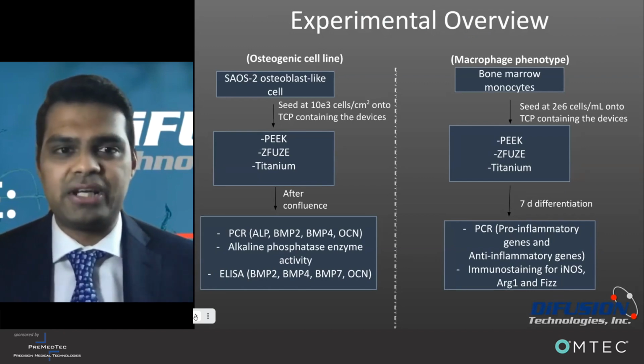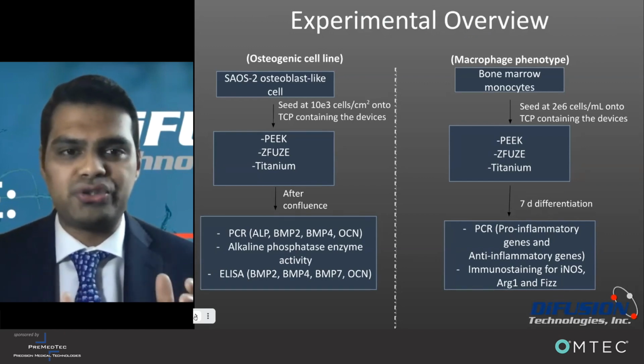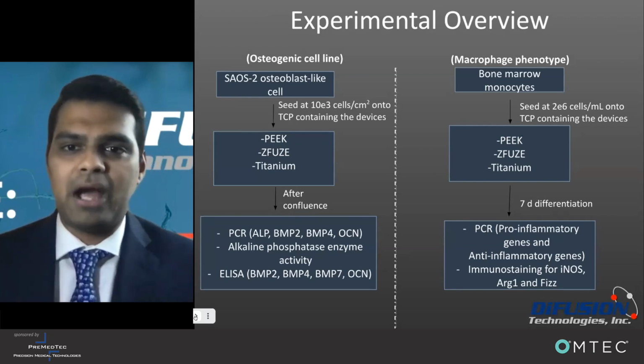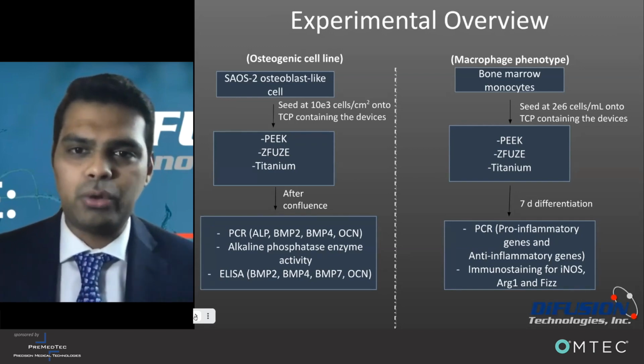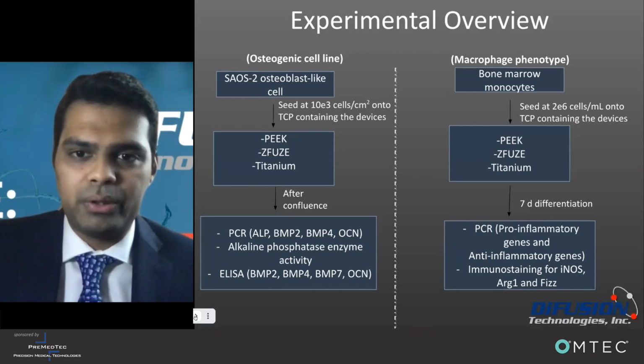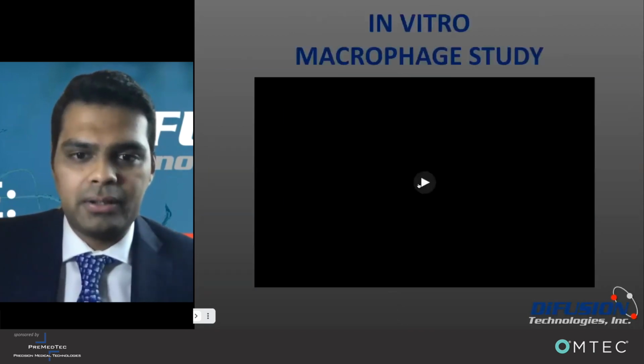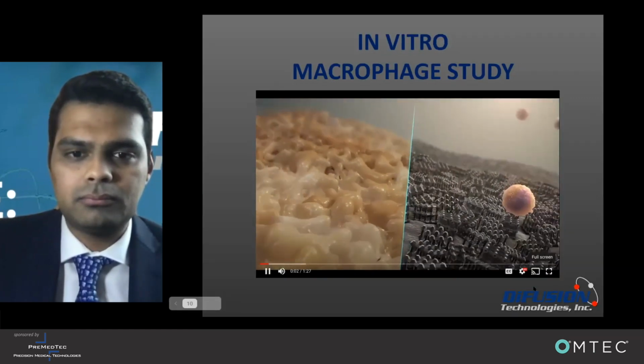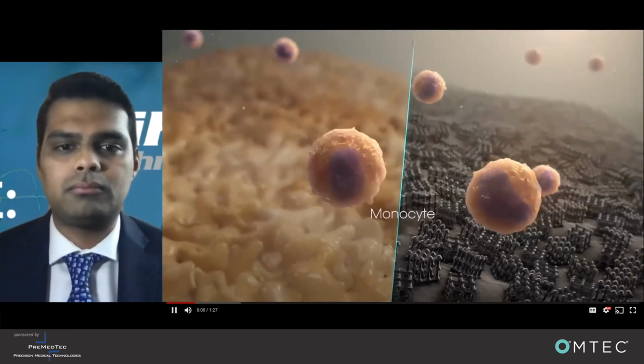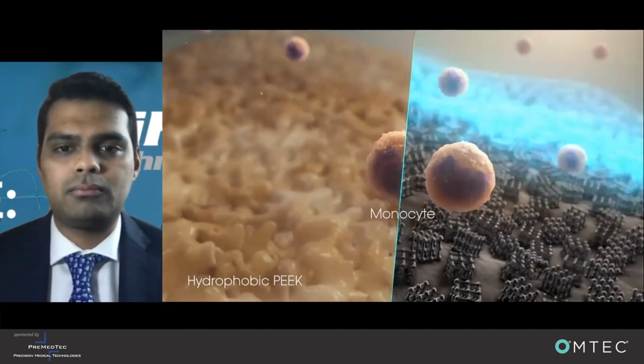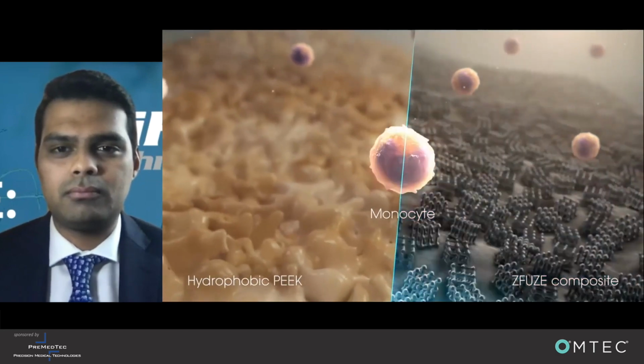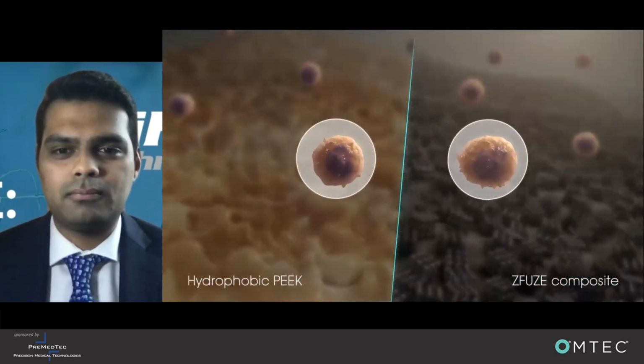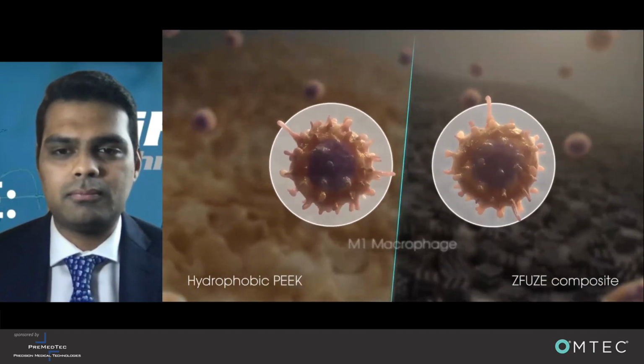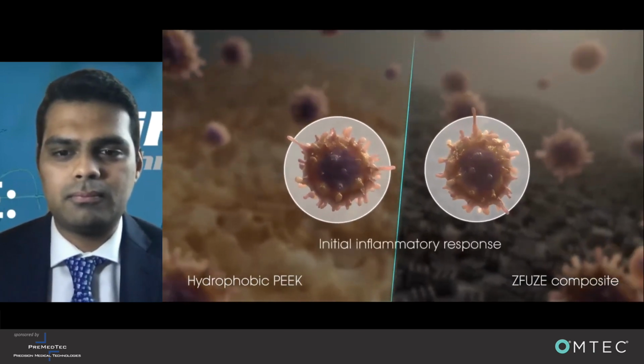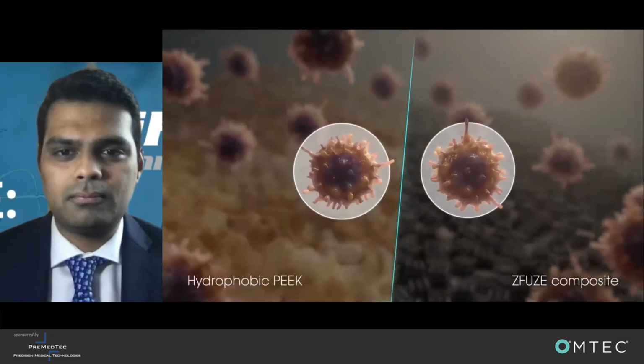We looked at the osteogenic SAOS2 cells, and we also looked at the macrophages. I'll quickly touch upon some of the results that we found from our macrophage study. As seen here, rat monocytes are introduced to conventional hydrophobic PEEK on the left and negatively charged hydrophilic ZFUZE composite on the right. The monocytes initially signal the M1 phenotype commensurate with normal wound healing and the routine initial inflammatory response to wound or injury.